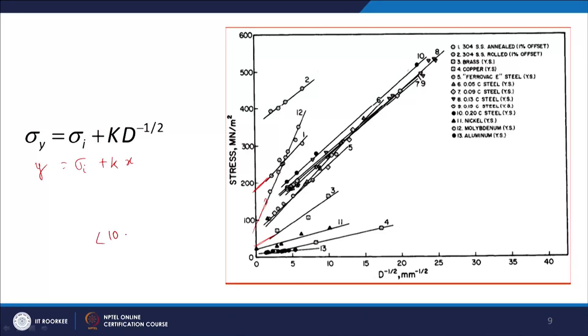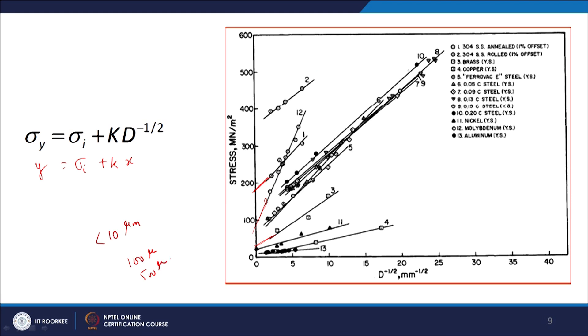To have grain size strengthening, you need the grain size to be in the range of less than 10 microns. For grain sizes larger than this, you will not see a significant effect of grain size on yield stress. For very coarse grain material — say 100 microns or 500 microns — if you want to see the effect of grain size reduction, it will not be very clear. When you start getting grain sizes in the sub-10-micron range, you will start seeing the effect of grain size on strength. Comparing 10 microns with 500 microns shows a clear effect, but going from 500 to 100 microns may not show any clear effect.